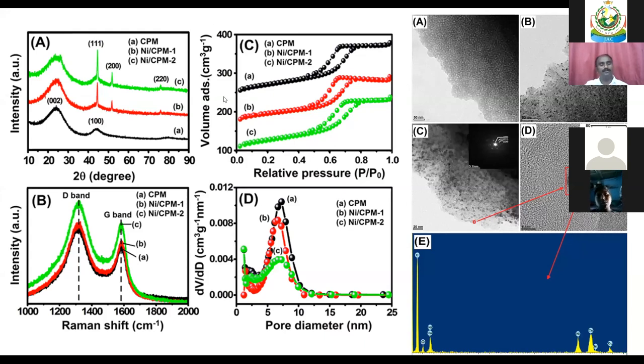Another thing is porosity. We need to study the porosity, that is the surface area measurement. The bare carbon, that is the CPM, the carbon porous material, you can see has a high surface area. And with nickel doped into the CPM, the surface area is somewhat reduced because the nickel atoms block some pores. Further increasing the nickel weight percentage, the surface area is lower. And this is the corresponding pore diameter profile.